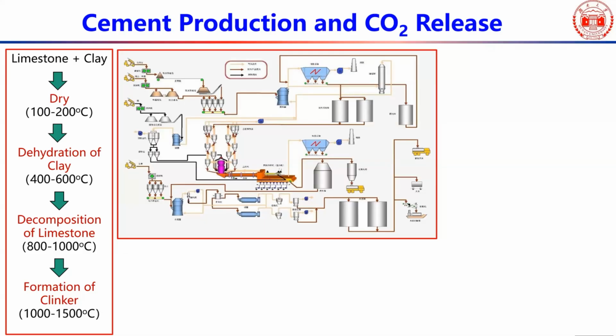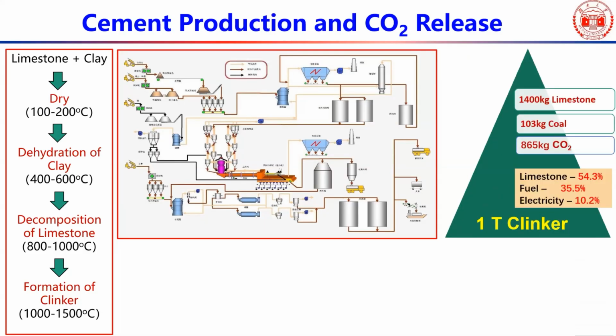So you can see, it involves very high temperature, but on the other hand, during the production, 1 ton of clinker consumes about 1.4 tons of limestone and 100 kilos of coal, and also, well, releases 860 kilos of CO2 for an advanced conventional cement production line. But now people are trying to use more and more alternative fuels or more waste material to replace limestone or other raw materials. The release amount will be less.